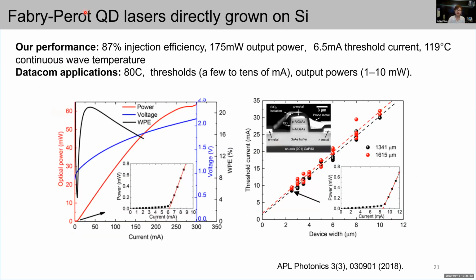For the most standard Fabry-Perot quantum dot devices on silicon, we have achieved this world record performance of 87% injection efficiency, 175 milliwatt output power, 6.5 milliamp threshold current, and operation up to almost 120 degrees C. Even today, it still represents the best quantum dot laser performance on silicon, and this can sufficiently meet the basic requirements for data applications, where it's desirable for a laser to have continuous wave operation up to 80 degrees C with tens of milliamps threshold and reasonable output power of 1 to 10 milliwatt.